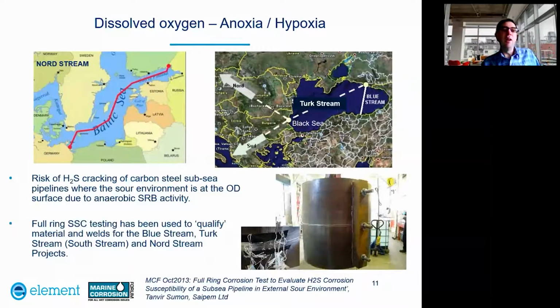Related to dissolved oxygen, some of the inland seas, examples here the Baltic Sea and the Black Sea, have anoxia regions where there are very low oxygen concentrations or zero oxygen concentrations. And this results in SRB activity at the seabed. So there is a risk of hydrogen sulfide cracking of carbon steel subsea pipelines where the sour environment is on the OD surface due to the anaerobic SRB activity.